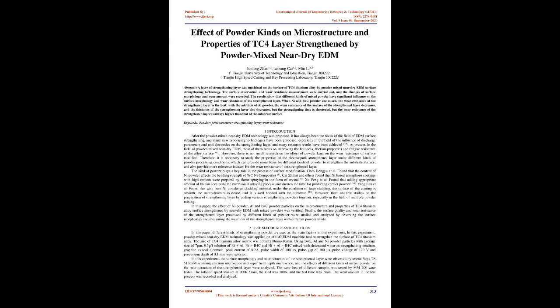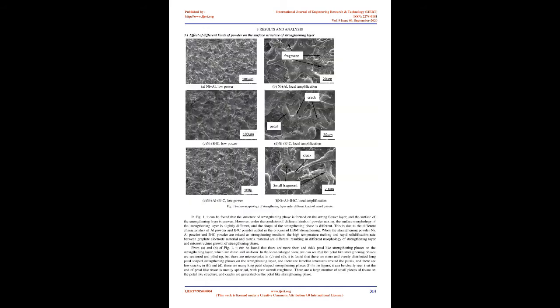Therefore, it is necessary to study the properties of the electrospark strengthened layer under different kinds of powder processing conditions, which can provide more basis for different kinds of powder to strengthen the substrate surface, and also provide more reference indexes for the wear resistance of the strengthened layer. The kind of powder plays a key role in the process of surface modification. Chen Hongyu et al. found that the content of Ni powder affects the bending strength of WC-Ni composites 8. Cai Haihei and others found that Ni-based amorphous coatings with high content were prepared by flame spraying in the form of crystal 9. Su Feng et al.